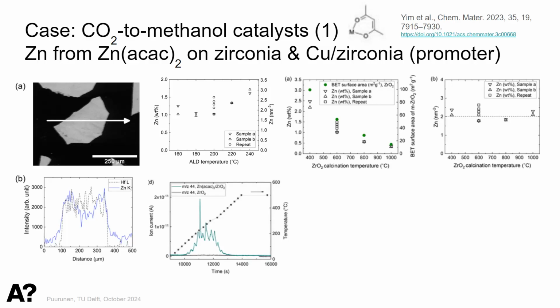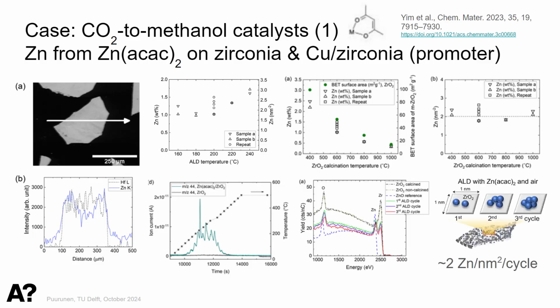If you then want to make cycles, to increase the zinc loading, then you need to remove those acetylacetonate ligands that are remaining on the surface. Typically, this is done with a heat treatment, and we have made an infrared study also, but this is with a mass spec looking at how CO2 is coming off at different temperatures. When we are above about 400 degrees centigrade, then we have removed those, we have burned them away. And we have made cycles, and the conclusion has been that we add about 2 per square nanometer in a cycle. And we also made low energy ion scattering analysis.